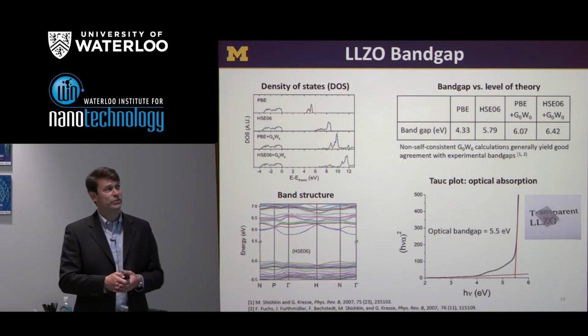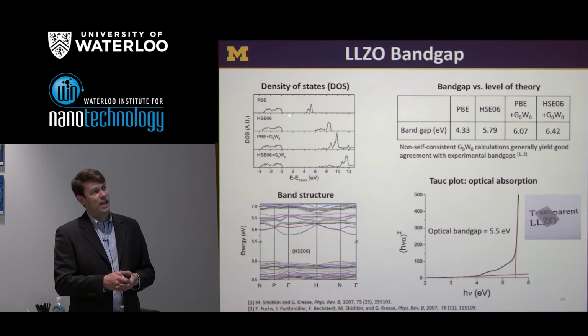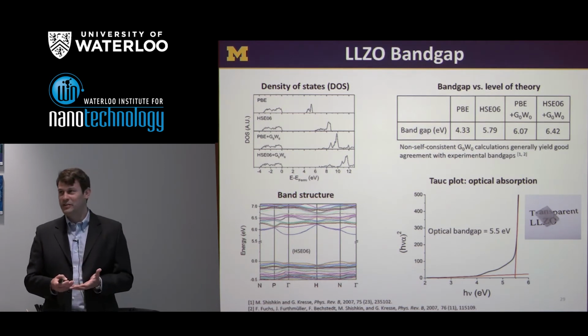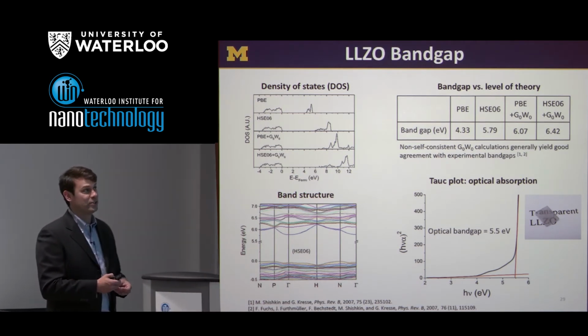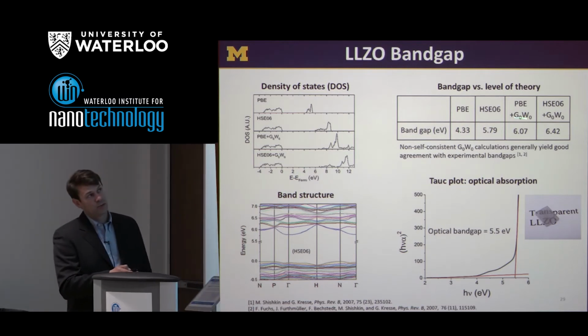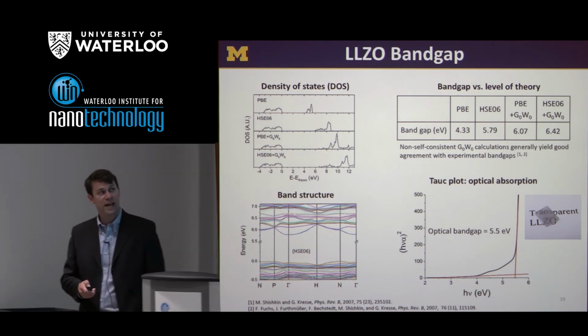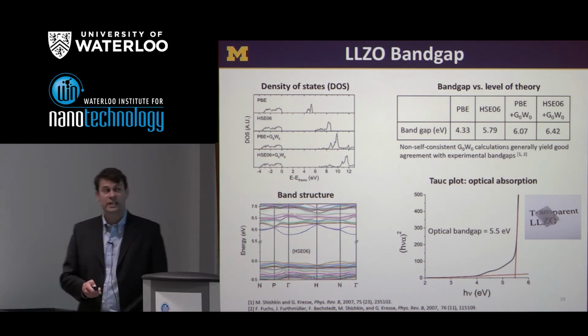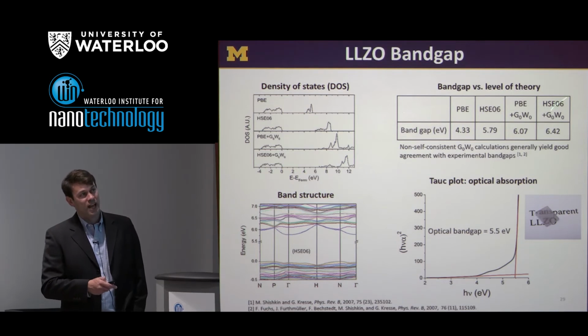So the first thing we did was look at the band gap. Here's an example of the calculated band gap of LLZO as a function of theory. And at the top here we have some ground state methods which we know will underpredict the band gap. But looking at some quasi-particle methods based on the GW technique, we get, this is probably a rather reliable estimate of the band gap, about 6.4 eV. So that's our best calculated estimate.